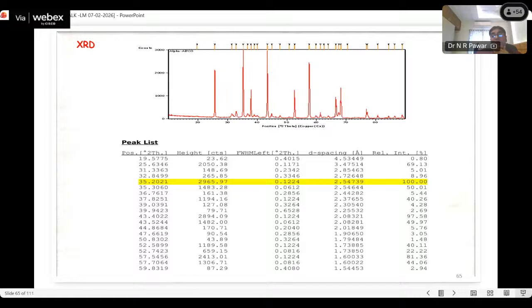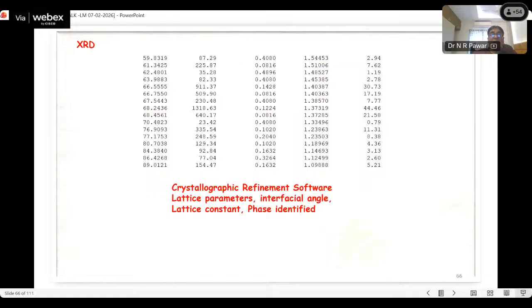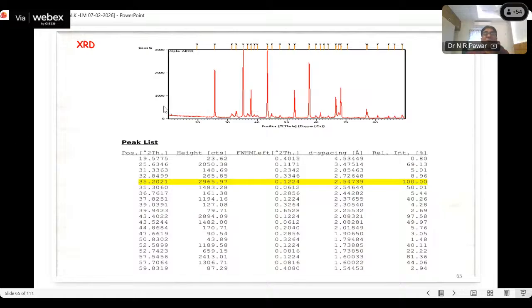Now, how can we find the grain size of that material? We consider the highest peak, the highest intensity. Then we consider the position of the theta. This is the theta, and now the data of the maximum peak, the value of theta and 2 theta. This is the position theta, and this is the intensity, and we consider the maximum intensity. I think this is at 35. Now we consider these values for the calculation of B that we have discussed in the Debye formula, that is the width of that.